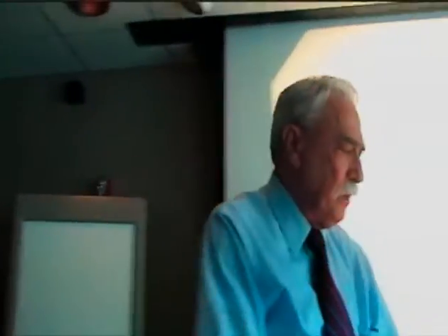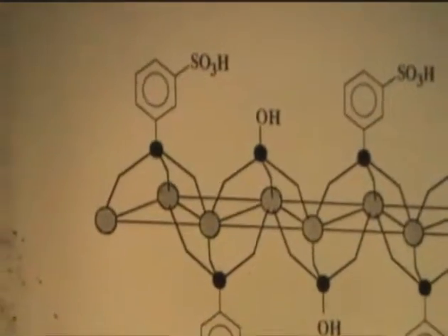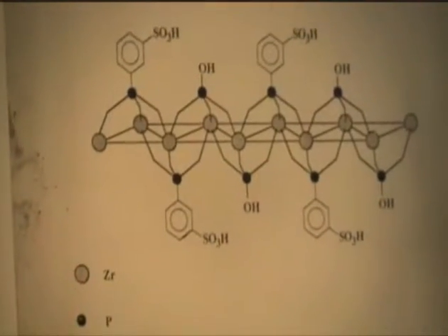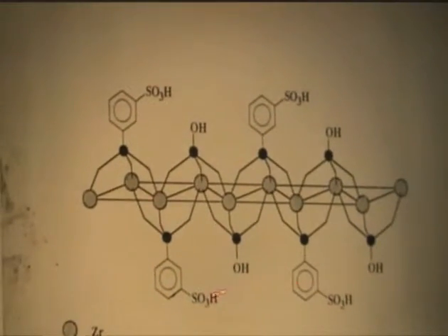to solve the structure. And then one of the things we did, and this shows some other things we can do, is the distance between these phosphorus is about 5.3 angstroms. So in other words, the phenyl groups are very tightly packed in there. So if we want to sulfonate this thing to get a Bronsted acid, we have to separate the groups.